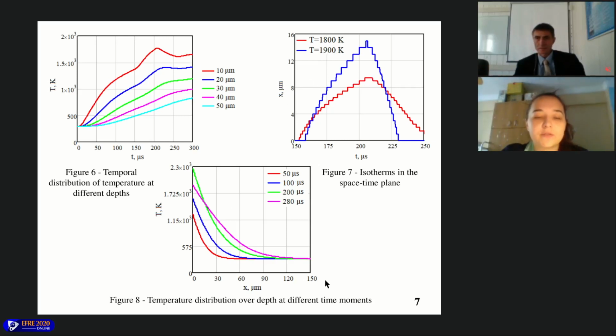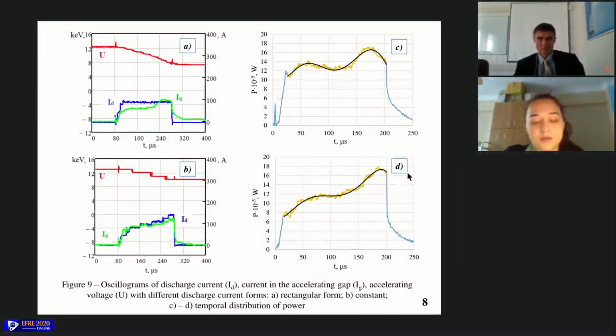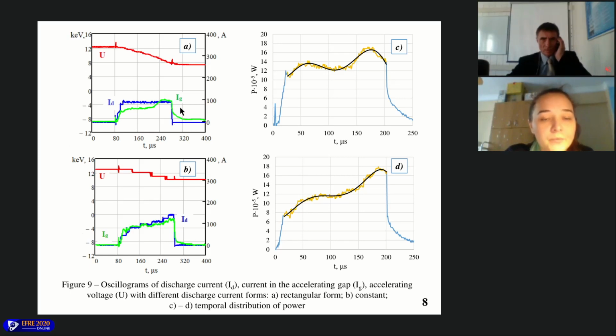And then on figure 8, there is a temperature distribution over depth at different time moments. As I mentioned before, by controlling the power density, we may control the temperature of the surface of our target. But there are actually several ways of putting energy into the target. For example, in figure 9, you may see the oscillogram 9A. There is a discharge current. By the discharge current, we control the current in the accelerating gap, and so in that way we control the form of the power during the pulse.